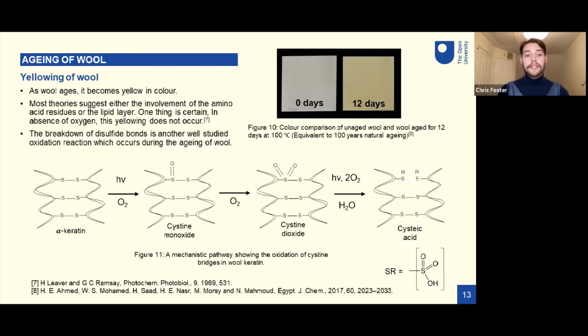Now, this you can see has the disulfide bridge where one of the sulfurs is double bonded to an oxygen atom. This can further react to create cystine dioxide, and this is where a sulfur atom is bound to two oxygen atoms through double bonds. The final step, which is in fact many different steps, actually breaks the disulfide bond and causes this product called cysteic acid.